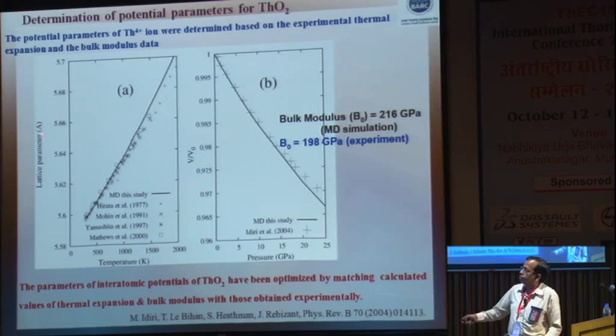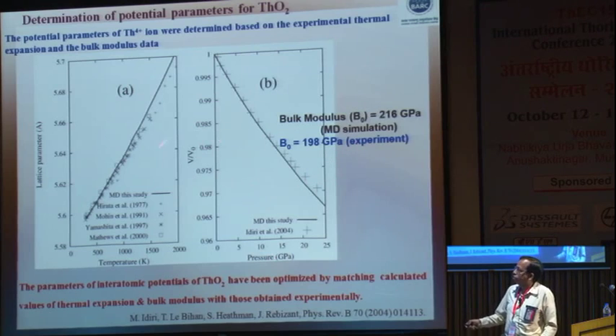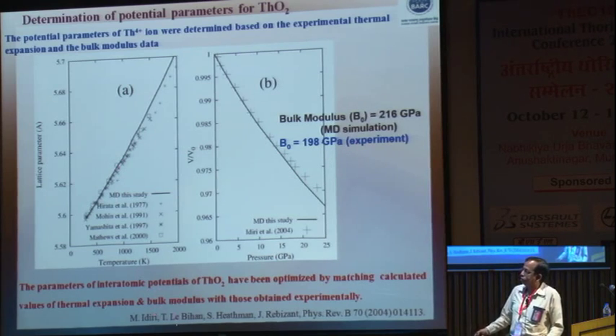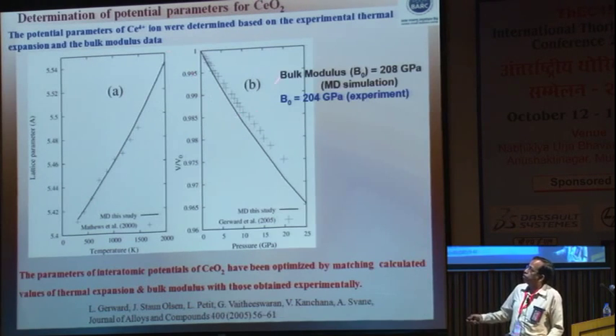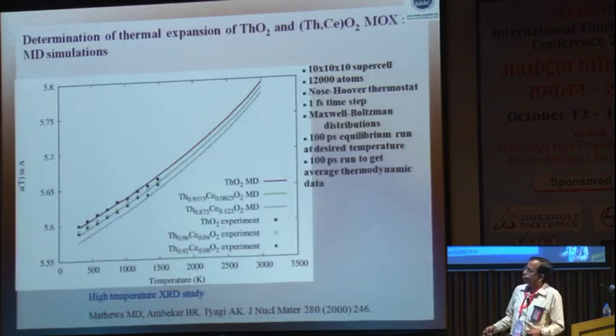So, this is the lattice parameter as a function of temperature and this is the bulk modulus as a function of pressure. So, both these quantities are used for evaluating A, B and C and that is what is mentioned here. This is for thorium oxide and the same exercise has been done for the CeO2 as well. The same set of parameters have been evaluated and have been compared with the experimental results.